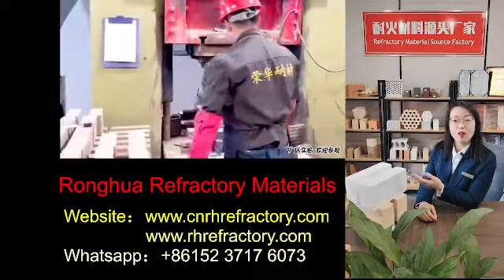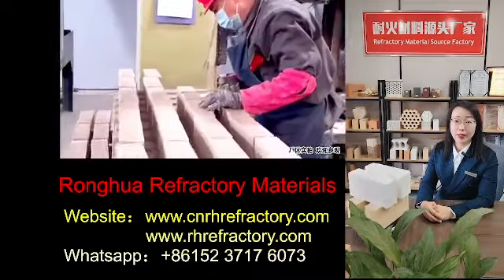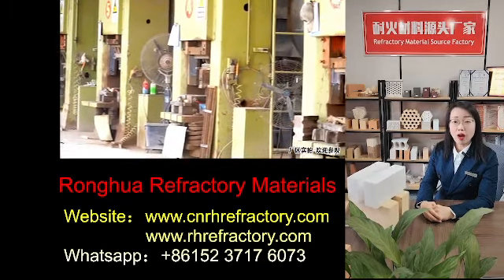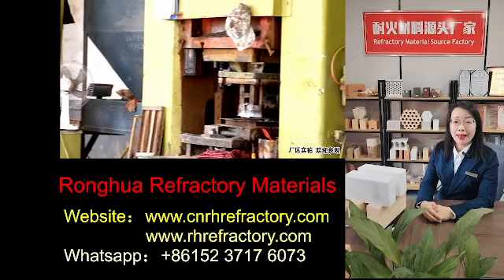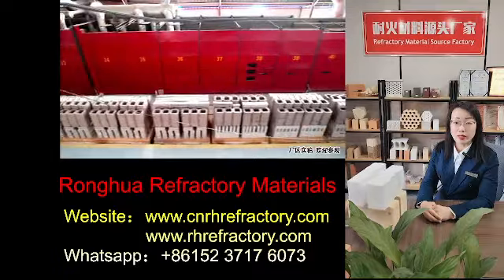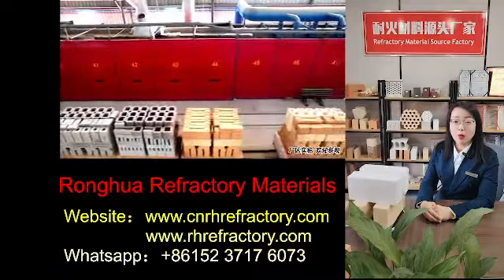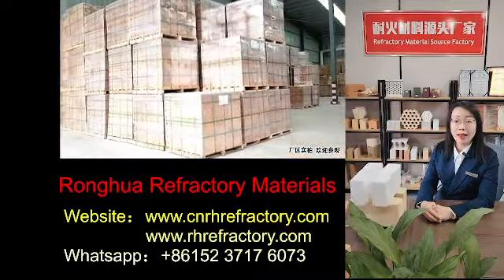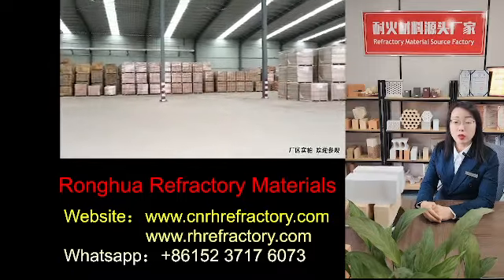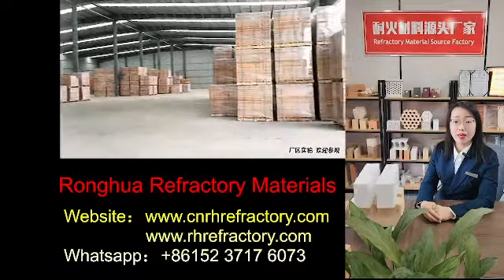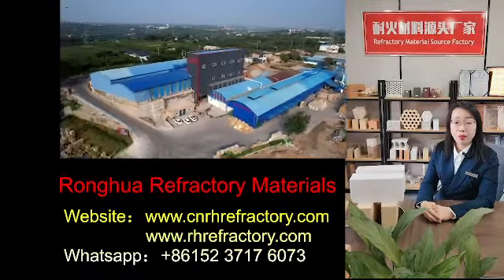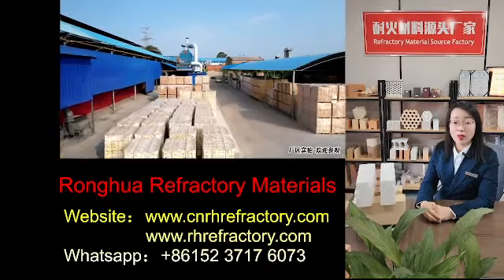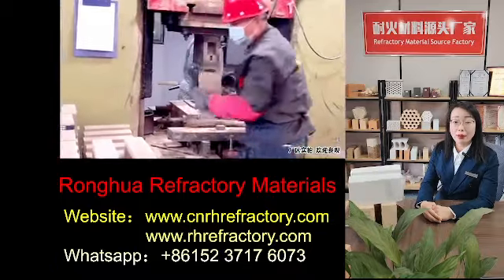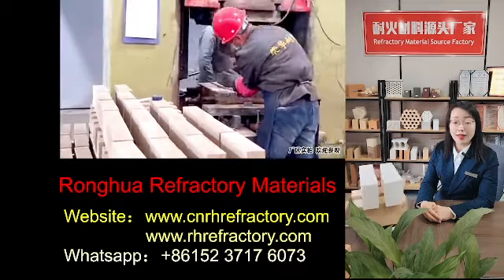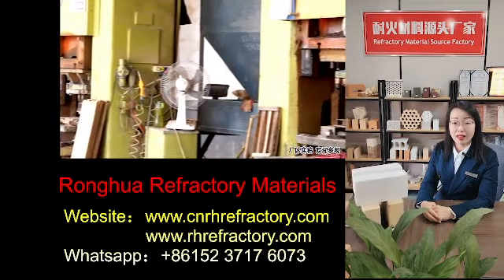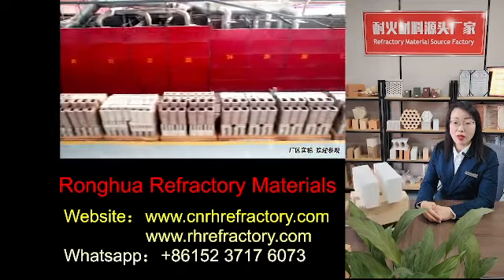Mullite insulation brick. The performance and refractoriness of mullite insulation brick is high. It can withstand a high temperature of 1800 degrees Celsius, but at 1600 to 1700 degrees Celsius, mullite insulation brick will start to soften and will not burn. However, it also has a high compressive strength at room temperature, in the range of 70 to 260 MPa. Good thermal shock resistance. Mullite insulation brick can be directly contacted with the flame, has the characteristics of high temperature resistance, high lightness, small thermal conductivity, and a remarkable energy-saving effect, and so on. It is suitable for the lining of various industrial kilns.